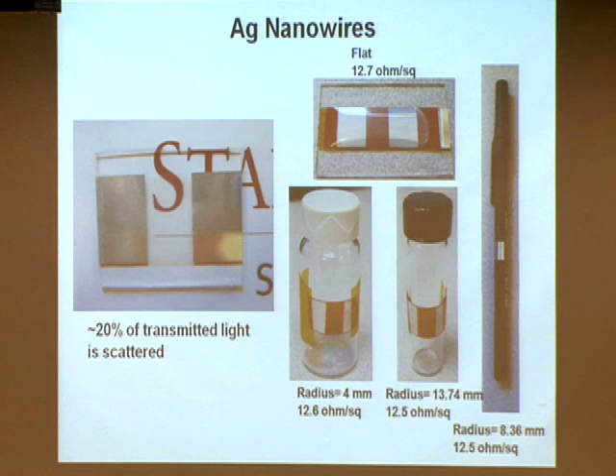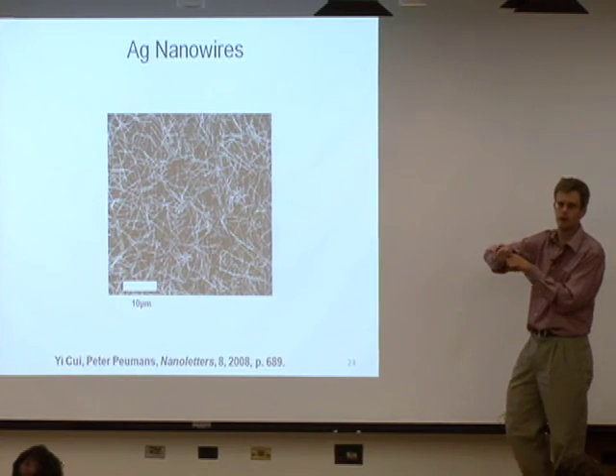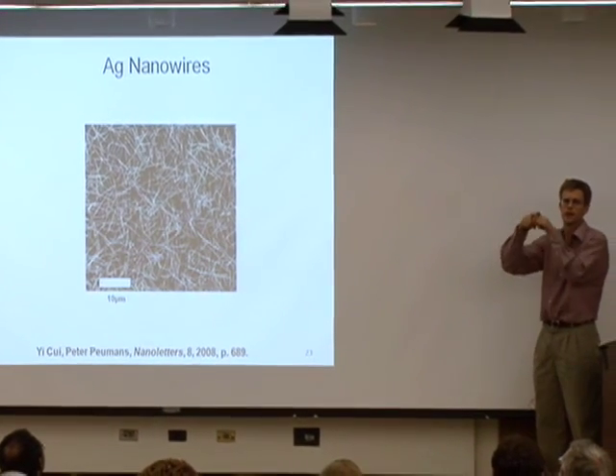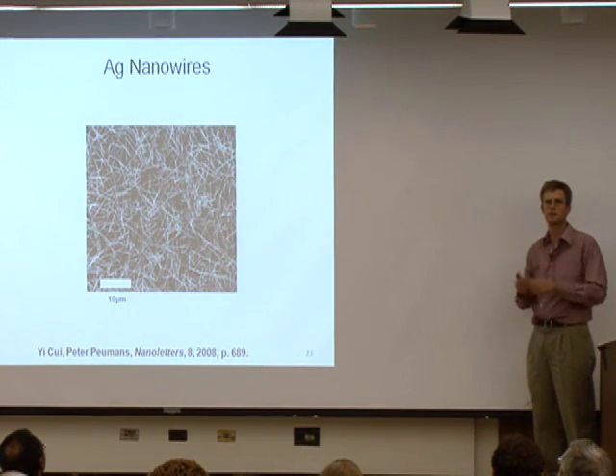The only problem with these films, the wires are fairly fat, and the spots where the wires cross are thick, and that can kind of punch up into the solar cell a little bit.